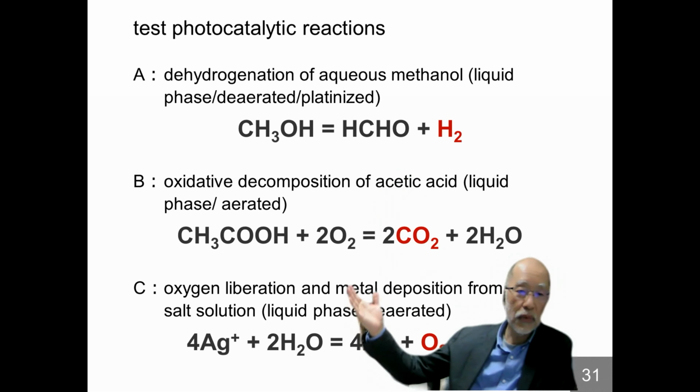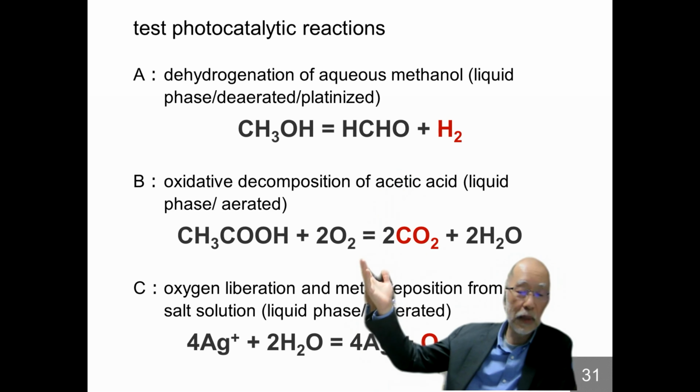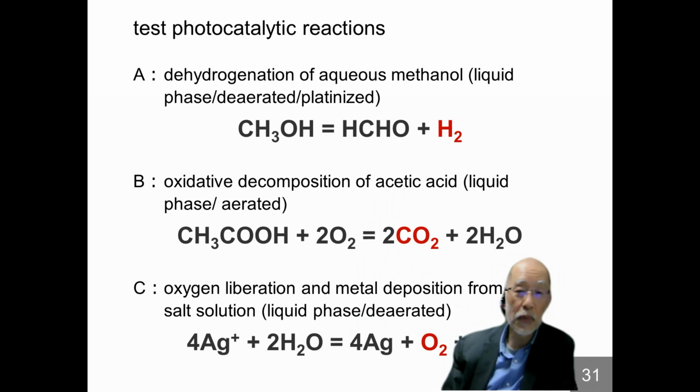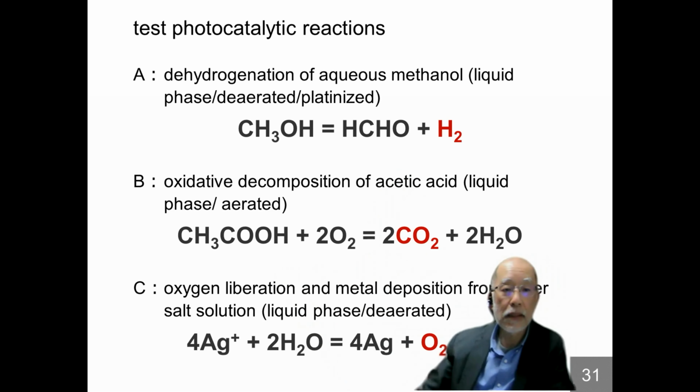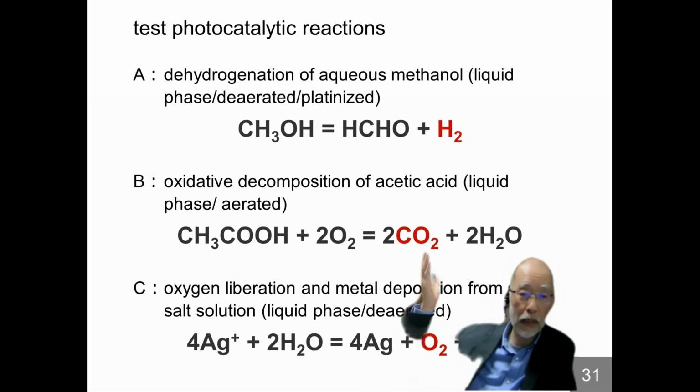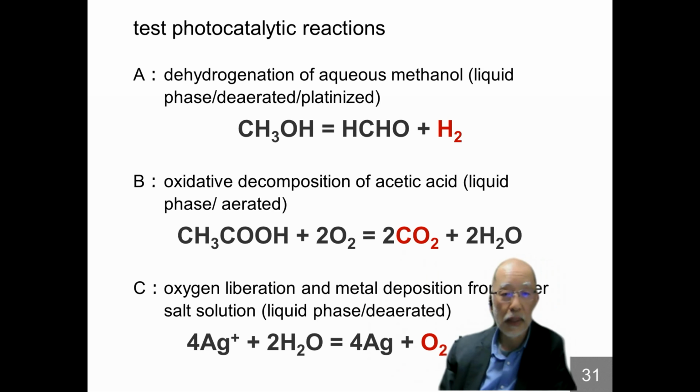And the second reaction is the decomposition of organic compound in aqueous solution. That is very popular in photocatalysis studies. We use acetic acid as a substrate, and the aerated solution of acetic acid is decomposed by using titanium oxide photocatalyst to evolve carbon dioxide.